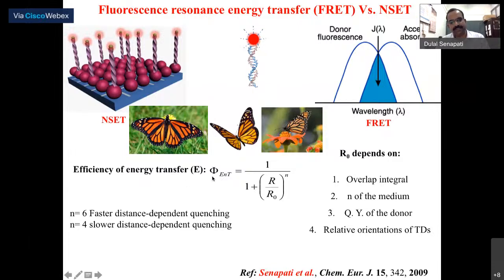The energy transfer efficiency, mathematically, we can explain by 1 / (1 + (R/R0)^N). Generally for organic molecule-based donor-acceptor pairs, N is 6. But for nanoparticle-based donor-acceptor pairs, it's actually 4, which we define as slow distance-dependent quenching. And instead of FRET, we call it nanoparticle surface energy transfer, or NSET.